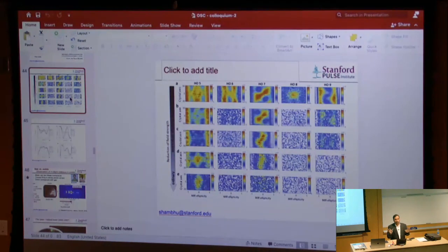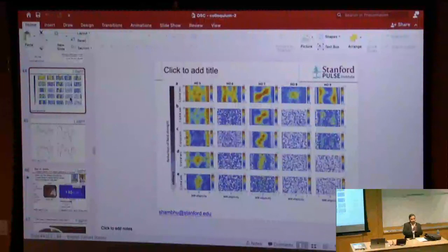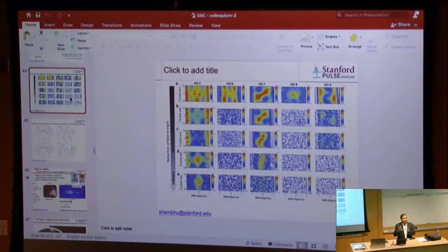So first of all, let me define how the strength of the material compares to the laser field we drive with. Let me give you one example. Zinc oxide crystal has a 3.2 eV band gap. The lattice spacing, the distance between zinc and oxygen, is about 3 angstrom. So the binding strength, roughly speaking, in that crystal is 3 eV per 3 angstrom, approximately 1 volt per angstrom. That's the strength of the material, the interatomic binding strength. The laser I used in the first experiment was about 0.6 volt per angstrom. So that's the comparison. And if you have a shorter pulse, you can drive even with a higher field. So the interatomic binding strength in the material is actually comparable to the strength of the electric field of the pulse. That's the first part of the question.